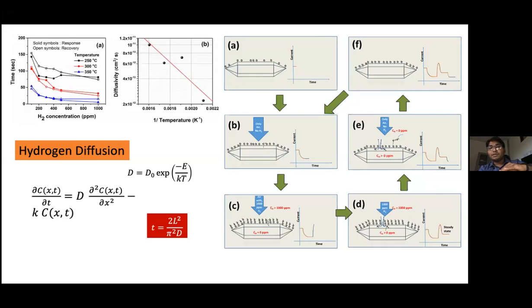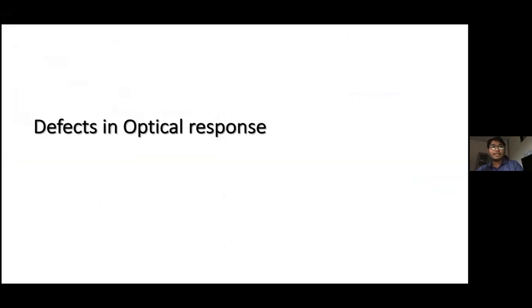So this hydrogen will reach some kind of a steady state, and then once you remove the hydrogen, things will go back to the native state where only oxygen is present. All the hydrogen will dissolve from the surface, leading back to regeneration of the current. This hydrogen incorporation is also a kind of defect, but that donor impurity may not have the same donor strength as the oxygen vacancy, which can donate 2 electrons. So the current may not actually come back to its original strength. So that's how we did this.